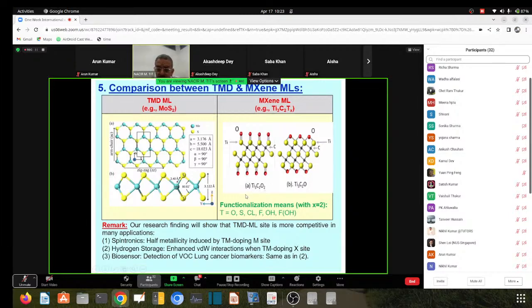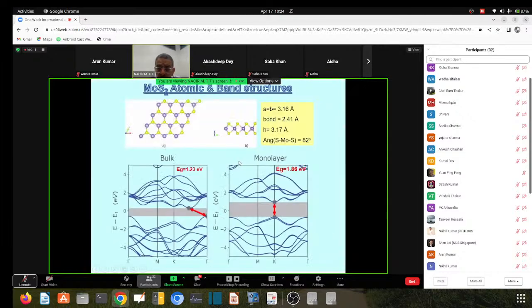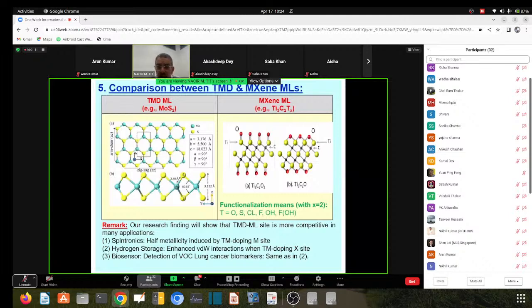So the most popular one, maybe the original one that was grown by Gogotsi, is Ti3C2O2, or maybe other, he has some different passivation. Usually fluorine elements are also there. So you can see here that they have this different perspective of monolayer. It is thicker than the transition metal dichalcogenide, and the topmost layers are metallic. So like here, the carbon is in black on the right-hand side, and the yellow colors are the metal, or titanium. So you have more layers of titanium, and the topmost ones are metallic. So the metallic layers are usually passivated, what we call functionalization of the material.